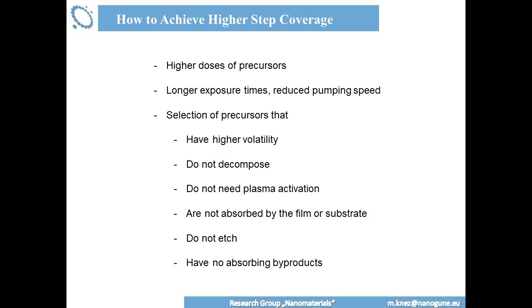You should really keep in mind some general rules for high step coverage. You need higher doses of precursors, of course. You have a very high surface area. Don't underestimate it. Small pieces of samples, they really can have a huge surface area. People really tend to underestimate that. You will need longer exposure times, and those exposure times are very much dependent on your aspect ratio.